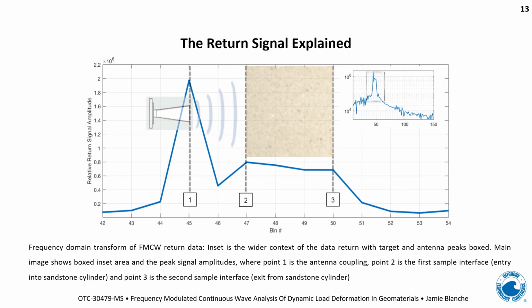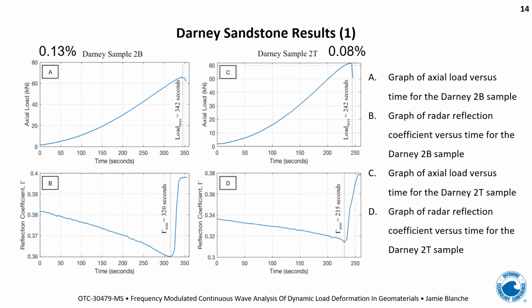Now, the inset shows you the peak amplitudes for this data set. Anything before the peak is noise from the waveguide, and anything after the peak is noise from the shadow of the target. The most important part of this graph is actually occurring at bin 48. That is where all of the data that comes subsequently in this presentation is taken from. In other words, bin 48 is the distance slightly inside the sample, and it's bin 48 which is where all the contrasts are coming from that are telling us what's happening inside the target. So now I'm going to talk you through the dynamic results for the Darney sandstone.